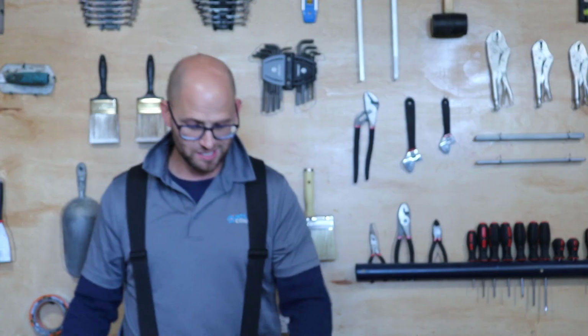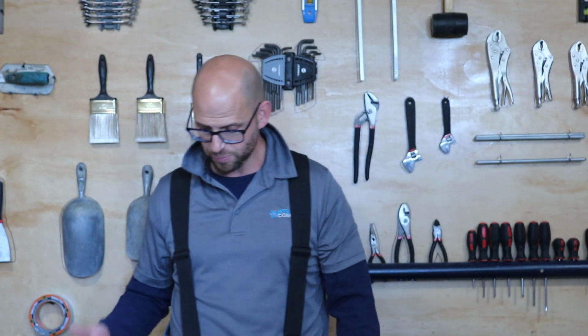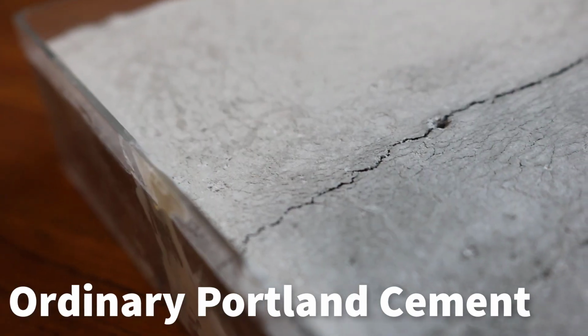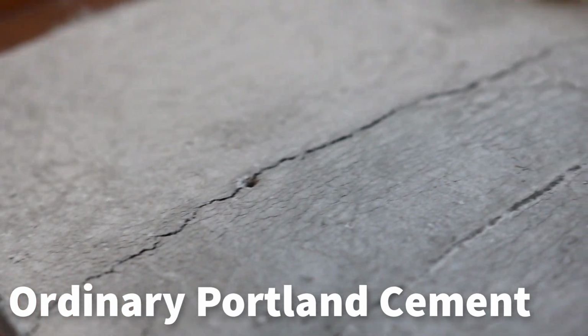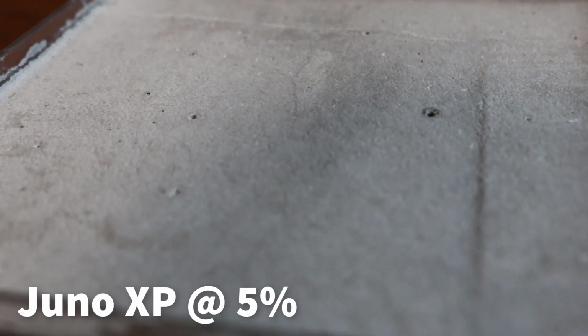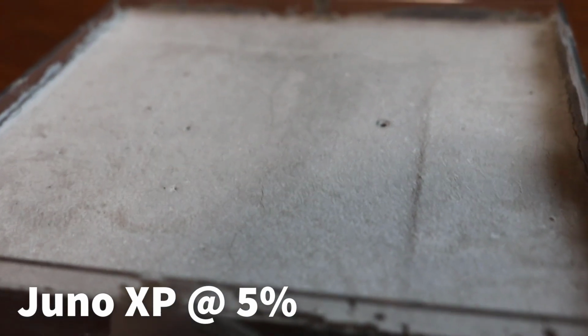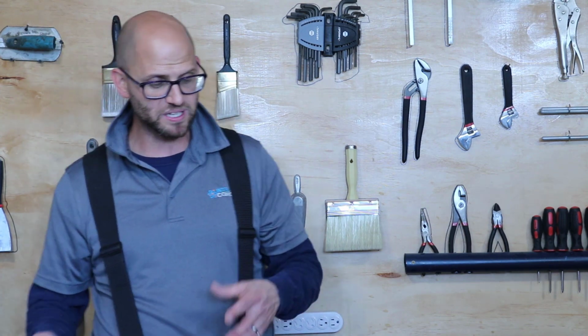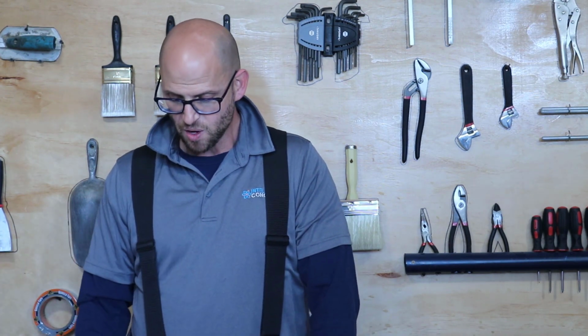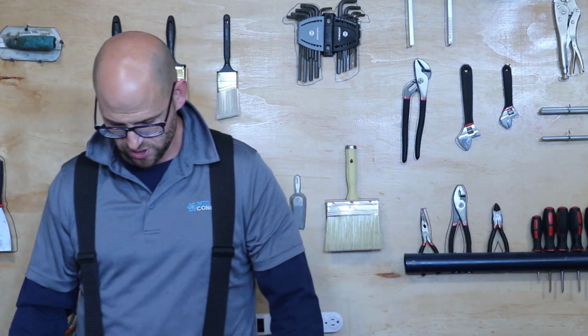And what you see here is basically how these two different samples, and these are 1 sample out of 3 samples that were used for the sample set, we can see that there is a major change in the size of the cracking. You can barely see the crack, although a crack is still there, in the Juno XP at 5%. And ultimately what we see here is that despite the fact that we're getting an increase in degree of cement hydration, and we see that through our increase in strength, through our compressive strength, but we're also getting a reduction in pore water migration that allows for that water to migrate over time, and of course that volume change.